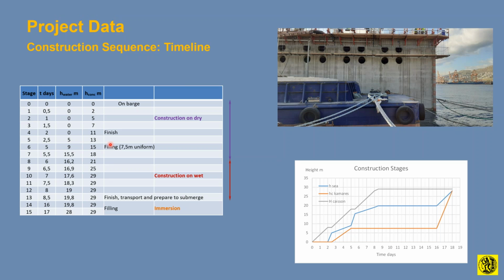are inside the water. From then on, the caisson starts raising more continuously using slip form in order to reach the final height of 29 meters, and at the same time, the additional ballast water is provided inside the caisson, so that eventually the freeboard remaining outside the sea level next to the port, you can see here, is about 7 meters, and the rest is floating inside the sea. So practically this caisson at the age of 3 days is already in seawater, the mud foundation and the bottom of the shear walls, the way it is constructed, 4 days.